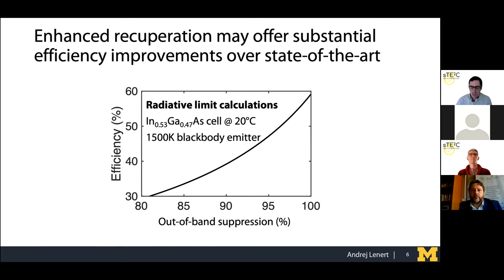So you might say 95%, that seems pretty good, but theoretical calculations will show that you can achieve much higher efficiencies if you go closer to 100% out-of-band suppression because of all of the power that's contained in that band. So if we look at a radiative limit calculation, at 95%, we're limited to 47% efficiency under these conditions. If we go, as an example, closer to 100% suppression, we can get to 59% thermal to electrical conversion efficiency. So you can see this is a remarkable gain that we can achieve with marginal increases in out-of-band suppression.